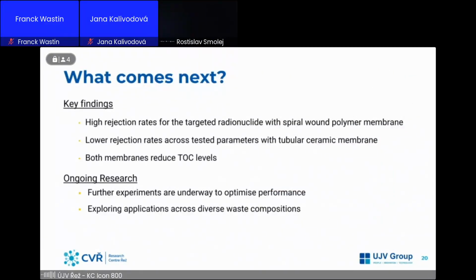So what we've seen so far is that the polymer membrane worked much better than the ceramic membrane. Both membranes reduced the TOC levels, which could mean that there will be no pre-treatment needed to reduce the TOC levels. But we will have to perform more long-term experiments to see if the organic matter doesn't add to the membrane fouling, which would then mean that we would increase the flushing amount and flush more often after smaller batches.